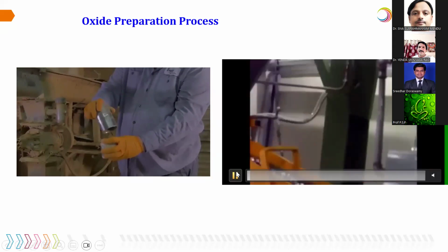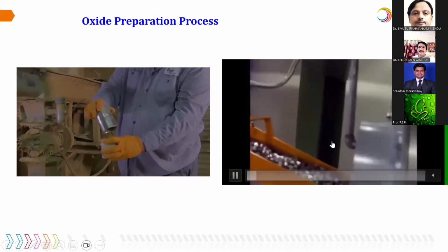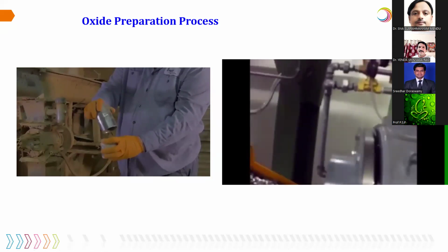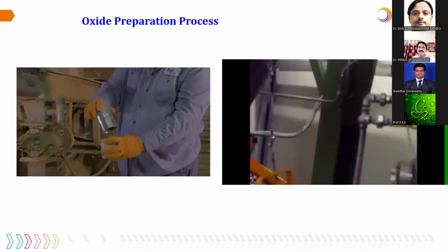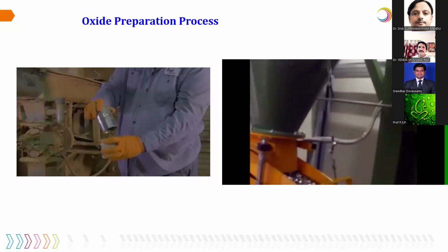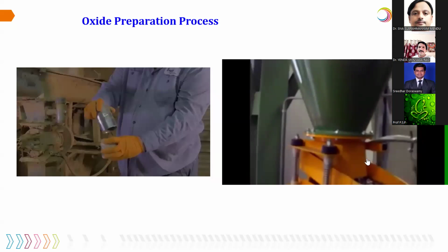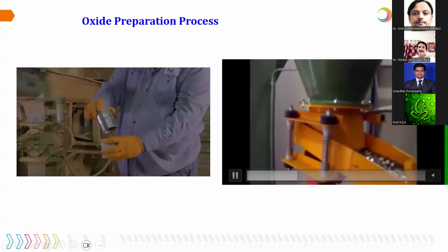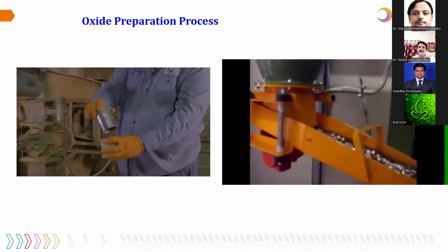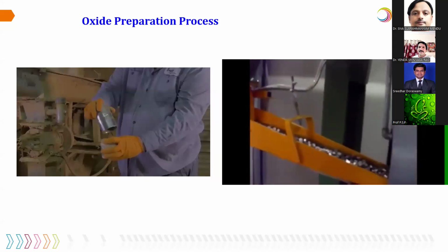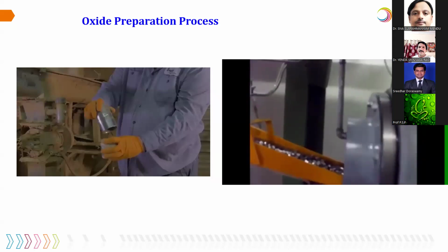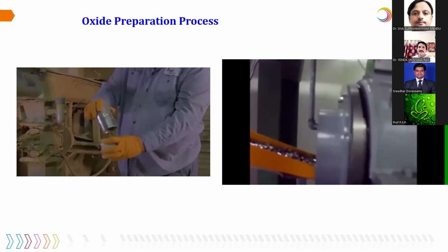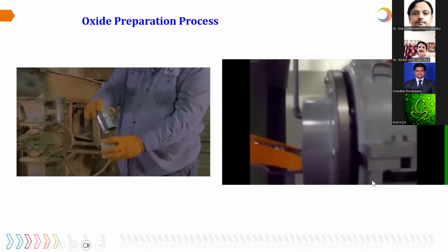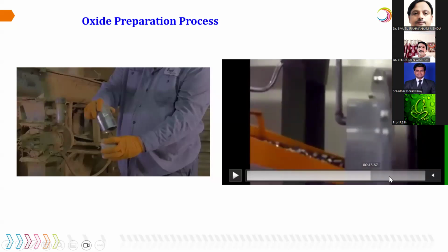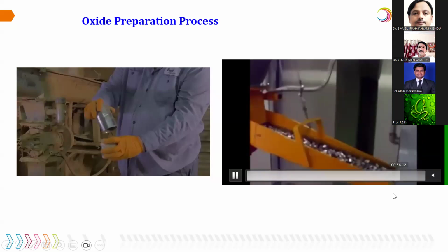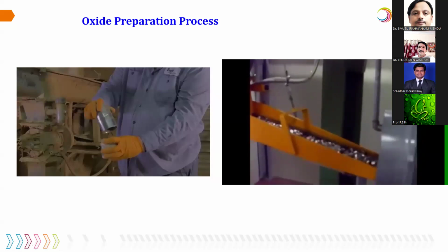The right side one is the ball mill process, and the left one is the Barton pot. This is the ball mill, where the lead ingots are made into small balls and then rotated at a desirable speed, where the lead metal converts into lead oxide powder. This is the horizontal or conventional ball mill equipment. This is how the active material, the lead oxide powder, is made.